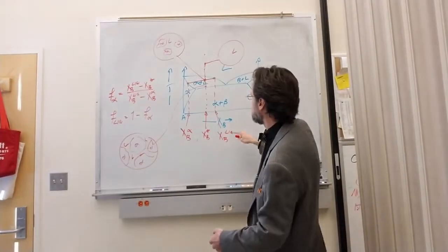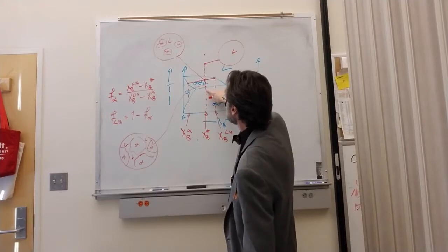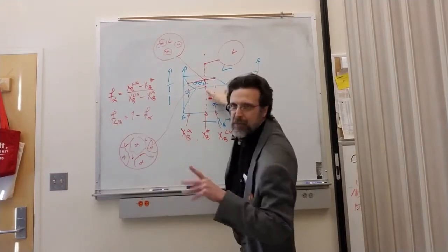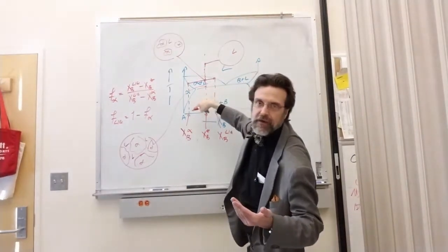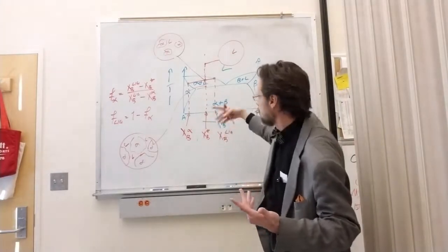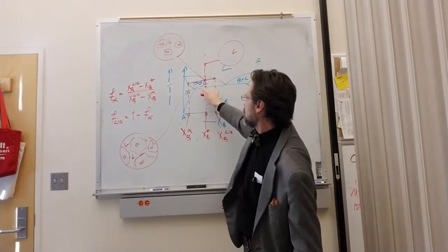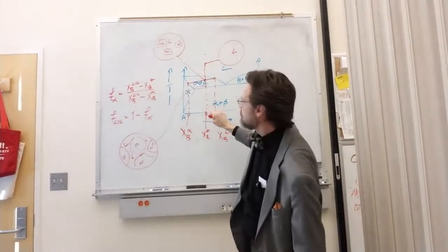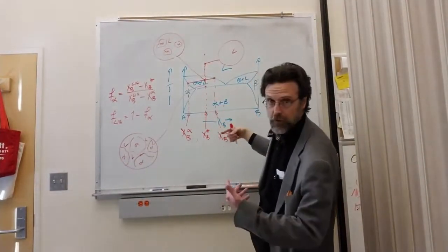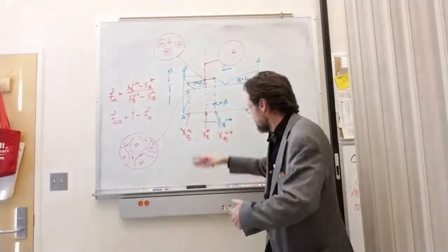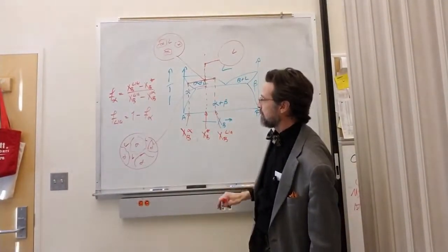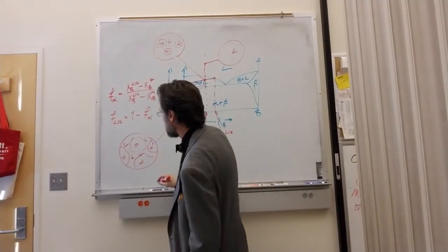And you say, well, how much? If we look at it, it looks as though we're about maybe 75% alpha and about 25% liquid. That's just eyeballing it, estimating what the phase fraction is. You can actually solve it by putting in the numbers, but roughly 75% alpha and 25% liquid.